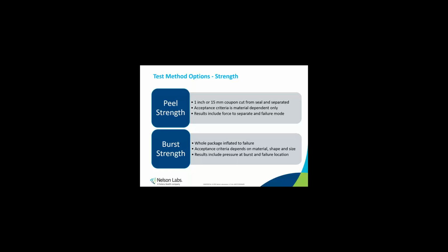Both these tests generate variable data, or a numerical value, and for both, you need a minimum value as the acceptance criteria. The strength minimum should be a value that's within the expected sealing capacity of the materials, and it needs to be sufficient to keep the package closed until the point of use. Both methods have some options in the standard, and if you're comparing data, like if you're checking to a manufacturer spec or comparing data from 2 labs, you need to use the same test options to get an accurate comparison.